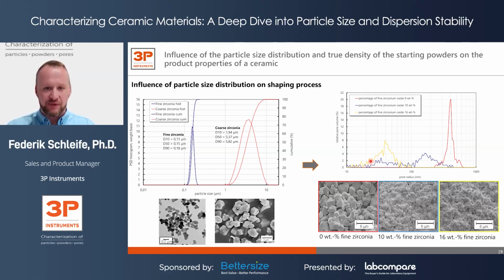So remember what I said before, the smaller the pores, the lower the sintering temperature, and next to it, it is desirable to achieve monomodal pore distribution to later on get higher sintering densities. It seems that the 16 weight percentage of fine zirconia and 84% of coarse zirconia seems to be the advantageous and desirable mixture here. So this could be further proved by checking the sintering process.